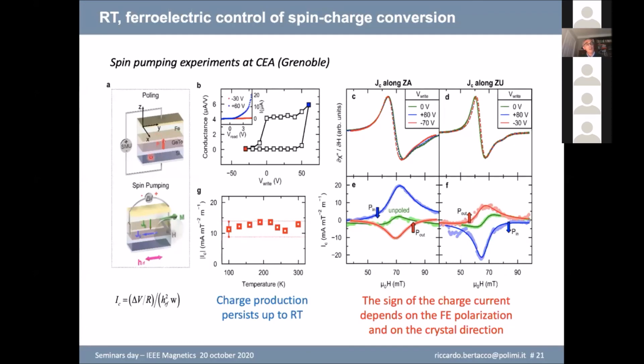Sara Barot, a student of our group, went to CEA in Grenoble. They cut some slices, and they were able to put them now in the cavity in order to apply some electric field in order to pole the germanium telluride layer, and also to measure by spin pumping the spin to charge conversion efficiency. As I told you before, the beauty of the story is that by applying different writing voltage pulses, we are able to follow what is happening. And here you see the typical conductance hysteresis loop, which corresponds to the fact that here you are in a ferroelectric state, and you can switch to the opposite ferroelectric state.